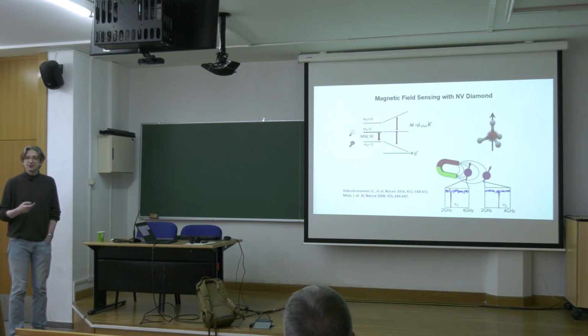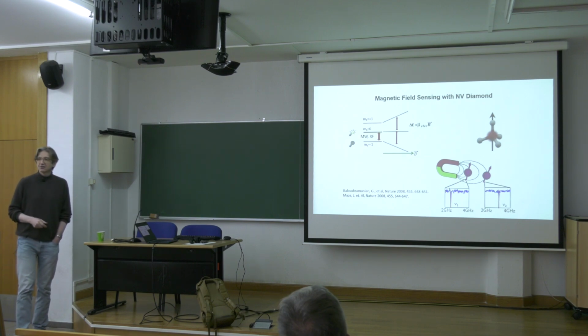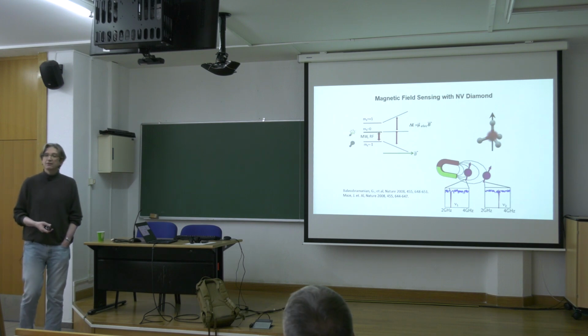And so this is a Zeeman effect-based magnetometer. This is experimental data here. You see two transitions associated with the 0 to +1 and 0 to -1 states. You measure the frequency and then you calculate the magnetic field. So what about the sensitivity of this approach?